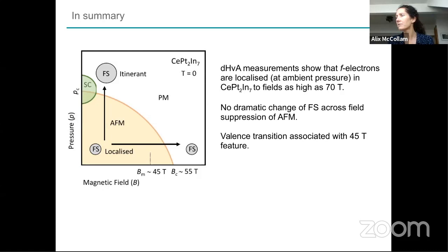Is there some modification occurring in the Fermi surface during high field that contributes to the oscillations? So in principle, any modification of the Fermi surface will show up in the quantum oscillations because, if it's a modification that changes the area, you will see it. If it's a modification that changes the density of states, or somehow if the renormalization is changed, you should see it in the temperature dependence or in the field damping. So there are a number of aspects of the de Haas-van Alphen effect that tell you about the quasiparticles on the Fermi surface and the shape of the Fermi surface.